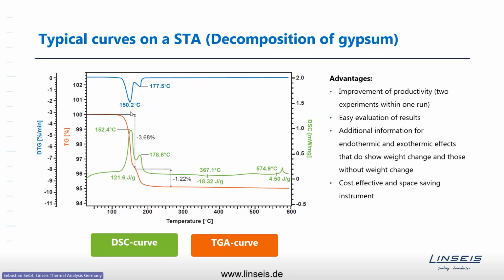So you can get information about how much mass is lost, what the content is, so what the humidity or water content of the sample is, and of course other decomposition reactions I will show you later. And simultaneously you get the green curve here, which is the heat flow. You see there are some peaks, which means at the point when the mass loss takes place, there is some heat flow change. So there is an exothermic or endothermic effect going on. The direction defines if it's endothermic or exothermic. And if you integrate the area beneath the peak, you also get a readout about how much energy is released, or in that case, how much energy is consumed.